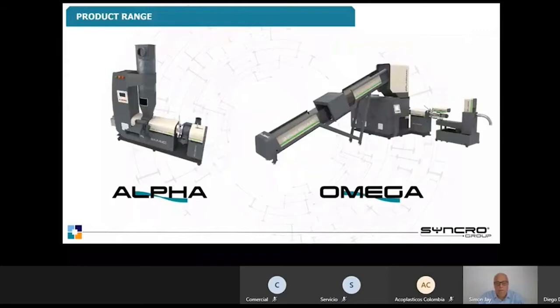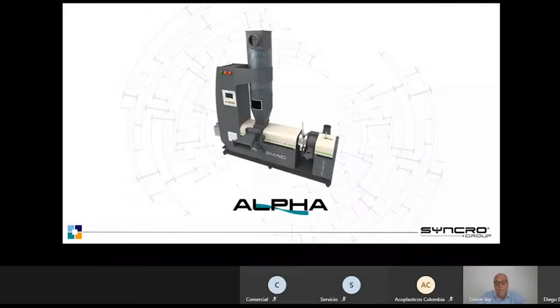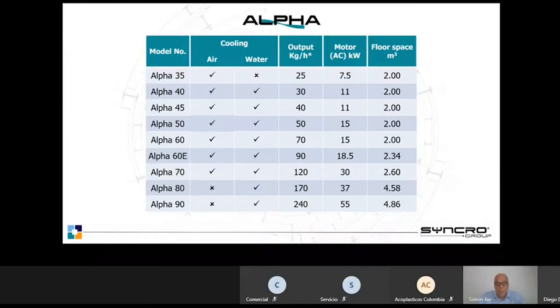In terms of our current product range, we have 2 machines. We have the Alpha and we have the Omega. I'd firstly like to take you through the Alpha machine. The Alpha machine comes in a number of different sizes, from the Alpha 35 up to the Alpha 90. The Alpha 35 is an air-cooled pelletized machine only. The Alpha 80 and 90 are water-cooled only due to their outputs, but the other machines in between can be either air or water cooled depending on the material that we are repelletizing. The outputs go from 25 kilos an hour max on the Alpha 35 up to 240, 250 kilos an hour max on the Alpha 90, but we can also go down as low as 4 to 5 kilos on the Alpha 35. The machines have a very broad processing window.